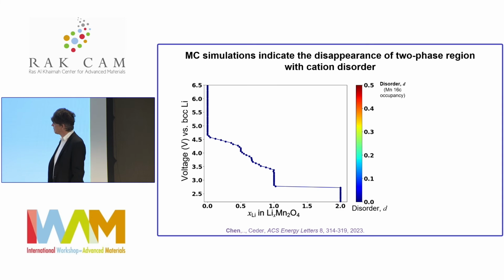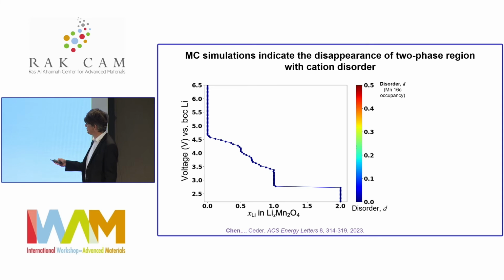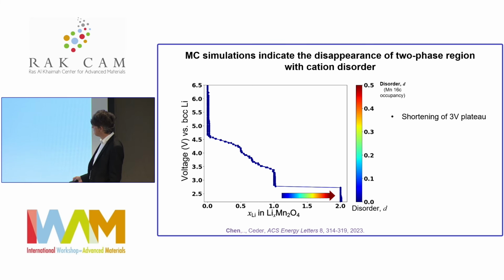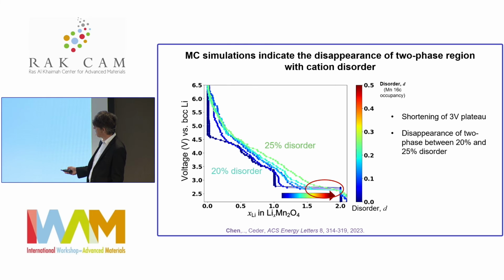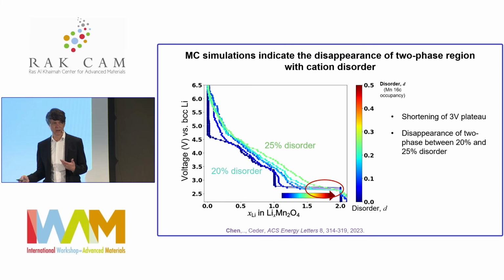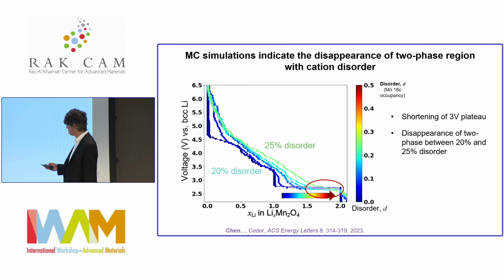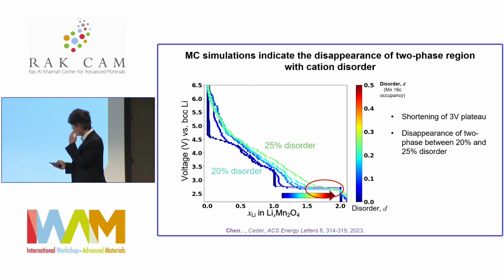And we did some theory. This is some ab initio simulations where we simulate the voltage profile, and this is what we're looking at. And we're systematically introducing disorder and see how the equilibrium lithiation increases. So first we make a very small amount of disorder on the 16C sites. We make more. What you see is this plateau is starting to shorten. You make even more. This plateau shortens more. And by the time you hit about 25% of disorder, so it's a very substantial amount of disorder, the two-phase region is completely gone. And you now have a material that can completely operate through solid solution and would be a much better cathode material.